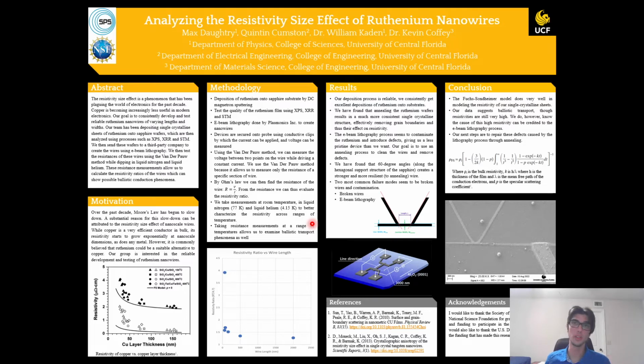So if the mean free path is longer than the wire itself, then it could, in theory, travel through the entire distance of the wire, or that section of the wire, without making a single collision, effectively having a resistance of 0. So what we'd expect with our resistivity ratio, the ratio of higher temperature resistivity to lower temperature resistivity, is a large increase in that ratio, because the mean free path is dependent on temperature. With a lower temperature, we have a longer mean free path, which means at lower temperatures, we're more likely to observe ballistic transport.